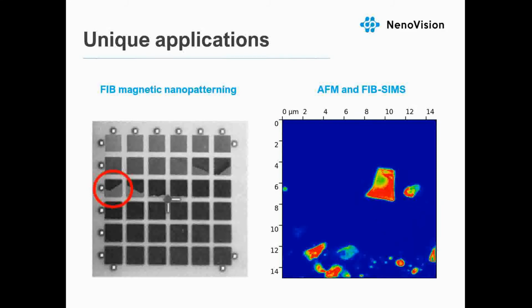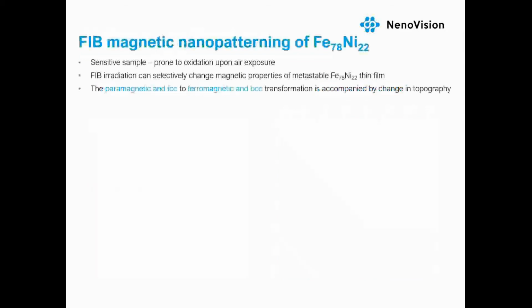In this application, focused ion beam was used to study direct magnetic patterning. A thin film of iron-nickel alloy was grown on a silicon substrate. This film undergoes a magnetic and structural phase transformation upon ion beam irradiation, and thus can serve as a template for direct writing of magnetic nanostructures by the focused ion beam.